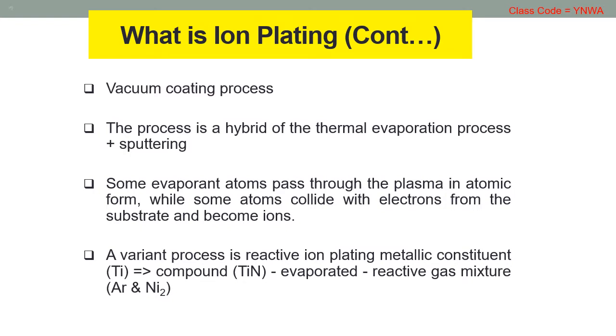the coating. A variant process is reactive ion plating, in which the metallic constituent, for example, titanium, of the compound, titanium nitride, is evaporated into the reactive gas mixture of argon and nitrogen that is enhanced by the glow discharge, depositing a golden-colored titanium nitride coating on the substrate. Films of titanium nitride are applied to a wide range of tools such as bits, punches, dies, taps, and so forth, to improve tool life by 3 to 10 times.